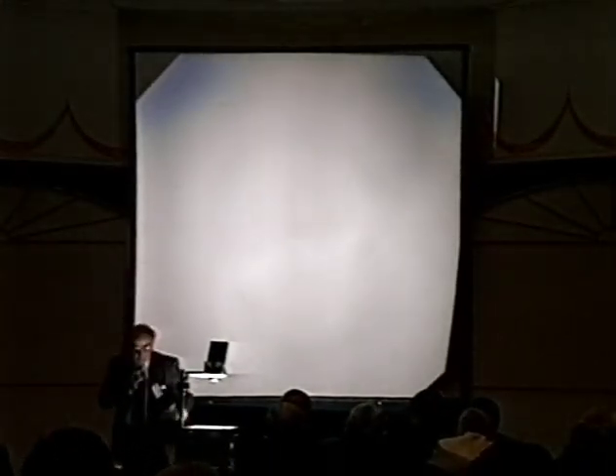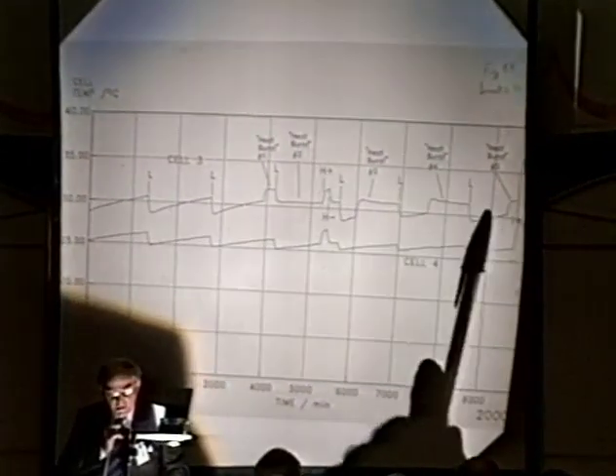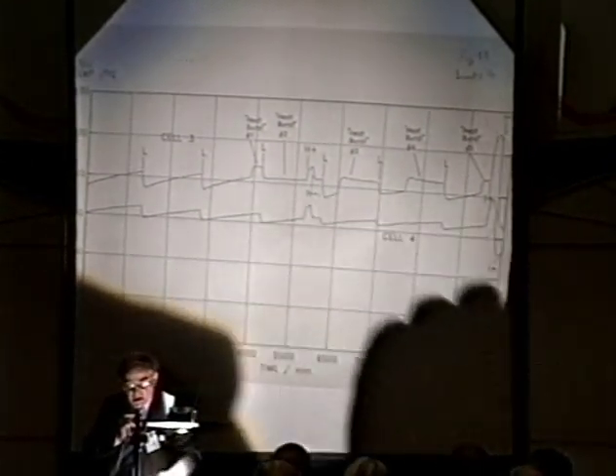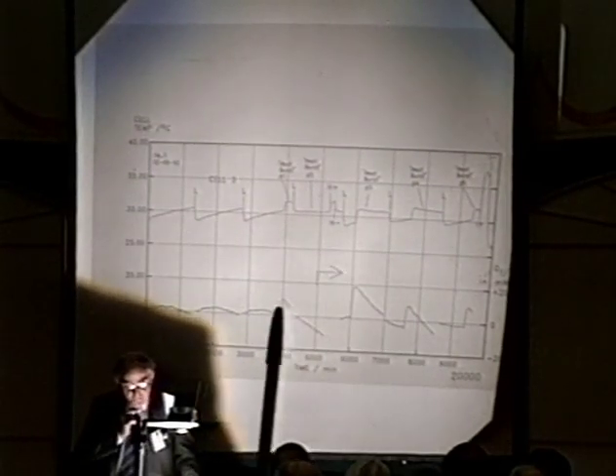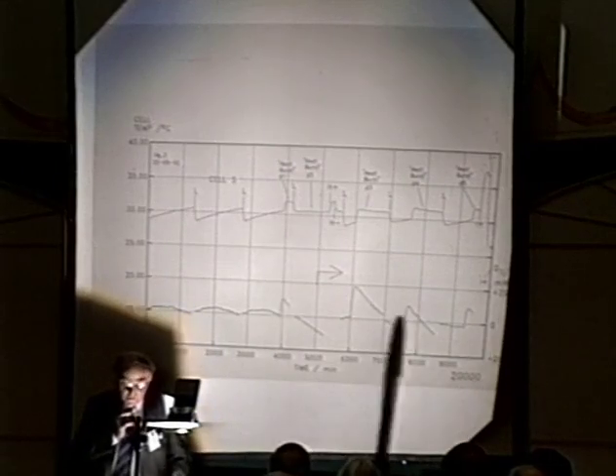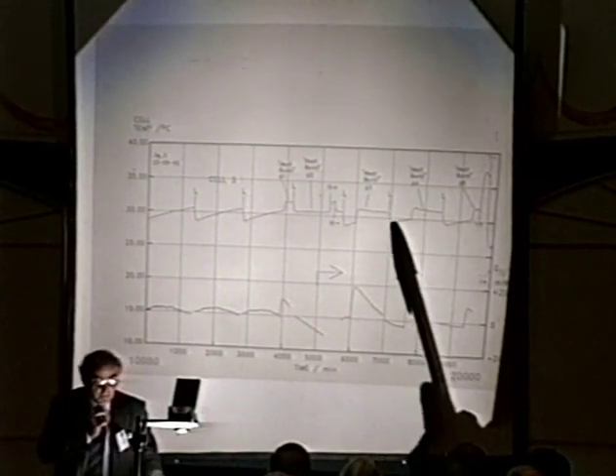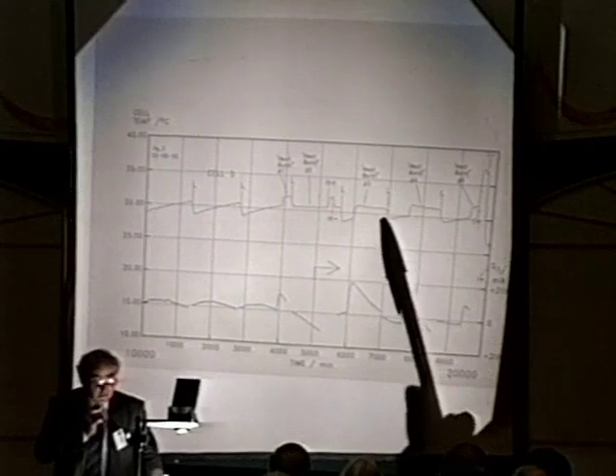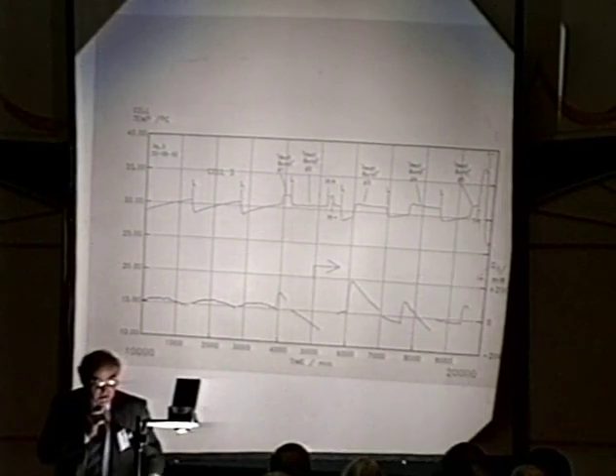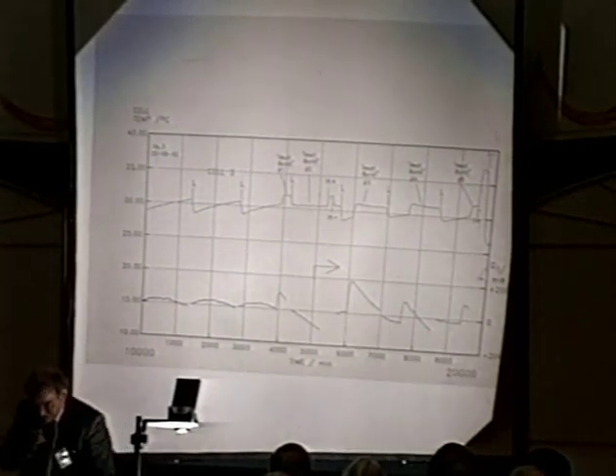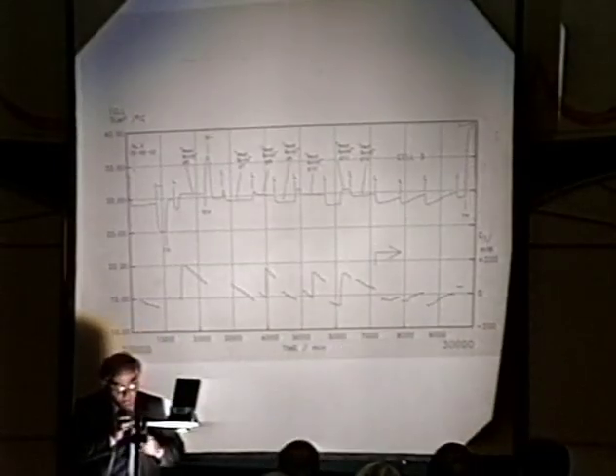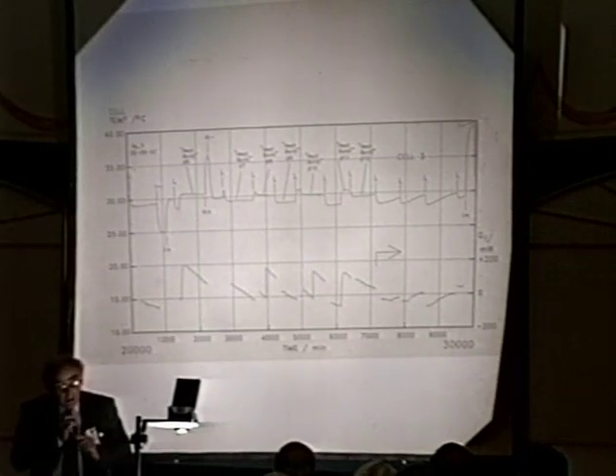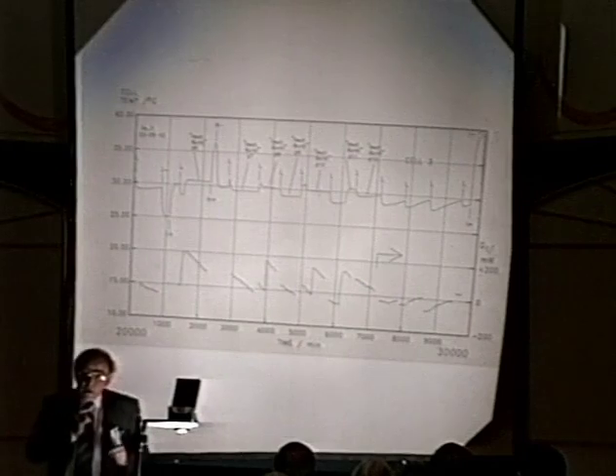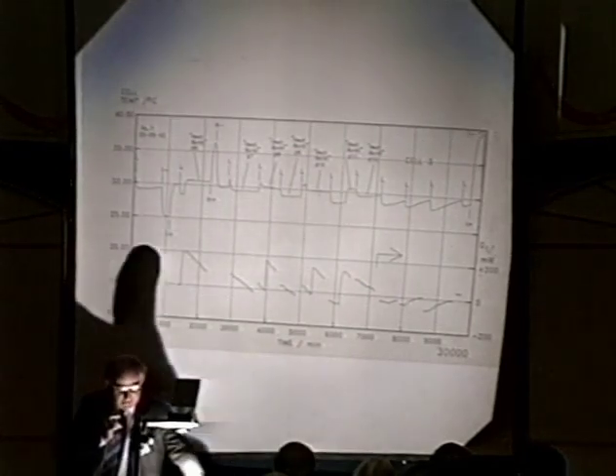So what we're going to do, just back up again, we're going to look at these, see what the thermal balance tells us along here. And it's really no very big surprise that we will get some excess energy, some excess enthalpy, and we do, whenever we have an excursion, we have an excess enthalpy. But of course, using this particular data processing strategy, we can only get the excess enthalpy with respect to a set 0 here. There may not be a 0 here. Each time we repeat this process, we set to 0. So we get about maximum about 200 milliwatts excess heat, excess enthalpy, and this goes on and on throughout the cycle of the order of 200 milliwatts, which is about the same as Stanley Pons and I had in 1989 at the comparable current density.